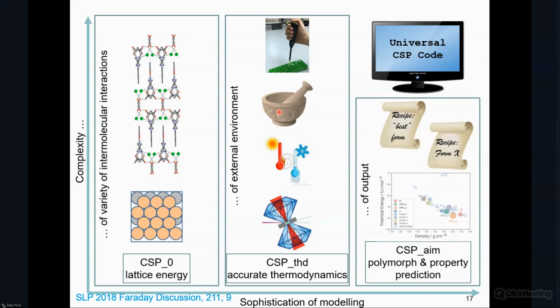But there are also other thermodynamic effects. Aurora Cruz-Cabeza has shown in some cases where the thermodynamic stability changes with the size of the crystallite, that you need to model the size because of the different energy of the surface structure relative to the bulk crystal structure, and relative humidity can make a difference to the thermodynamics. But as we're also over-predicting here, it's not just thermodynamics that counts. It's the relative kinetics of the nucleation and growth of the different competing polymorphs that need to be favorable to find a given polymorph.